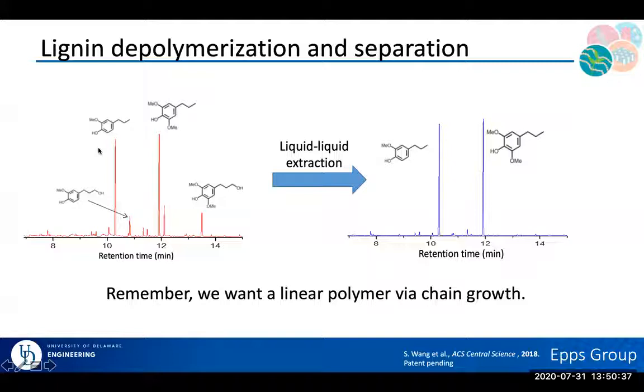So how do we do that? We did one separation step. And that one separation step was liquid-liquid extraction. We can use hexane and water, a little bit of methanol in some cases. And we actually then end up with a GC that looks something like this. And so this is quite nice because what you can see is that we now have just our 2 primary products. No column chromatography or other separation approaches are needed.